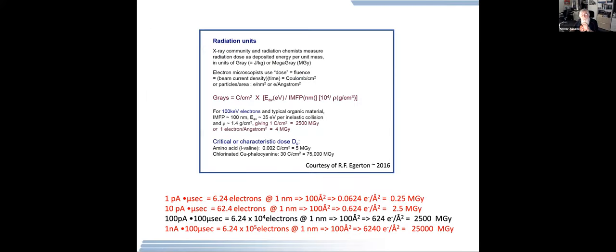But what I'd like to remind everybody about is the radiation units that we're interested in. Depending on what community you're in, whether you're in the X-ray community or the electron community, the X-ray community likes to talk about grays. We like to talk about electrons per square angstrom or whatever. I think the important parameter that I like to remember is one picoamp in 1 microsecond is 6 electrons. And if we take that and multiply it by the area of the beam, we can get a number for the number of electrons per square angstrom. So a picoamp times a microsecond is 6 hundredths of an electron per square angstrom if we have a 1 nanometer beam.